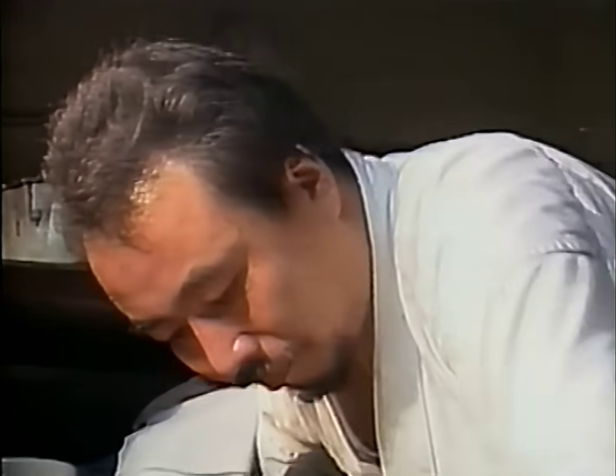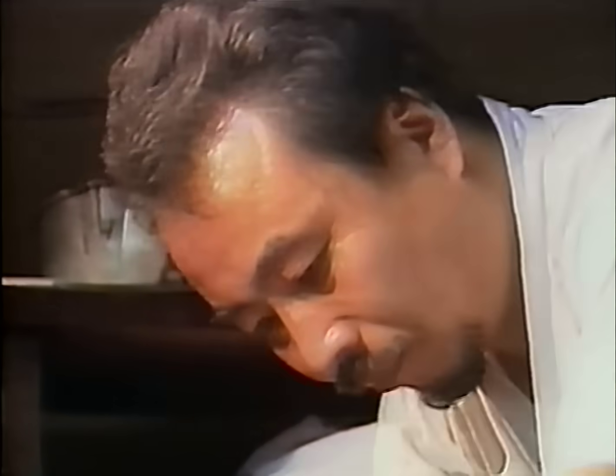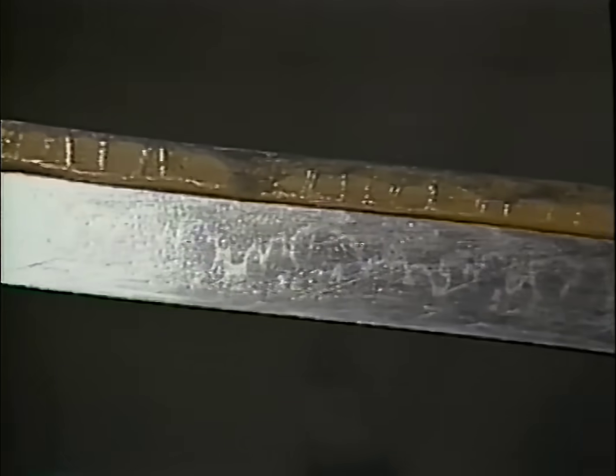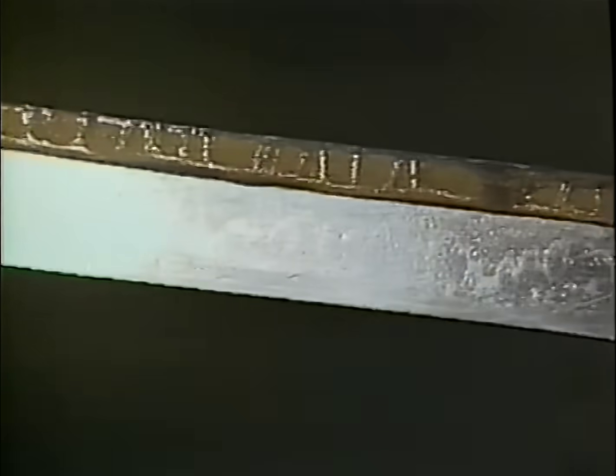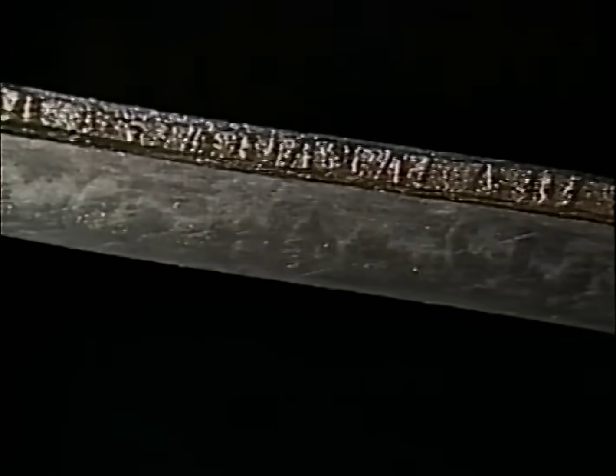After further treatment to clean off the clay, we reach the crucial moment when the hamon is revealed. The clove blossom line should be very clearly visible on the blade. At this point, Yoshindo can tell whether yakiire has been a success or not.